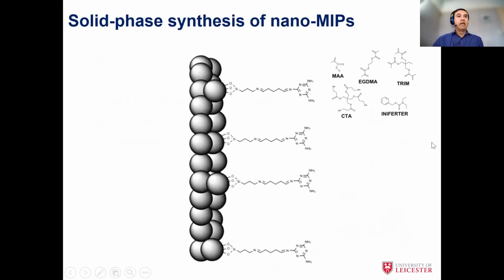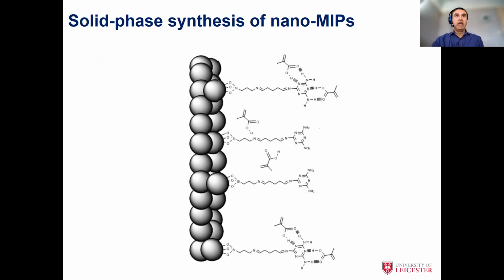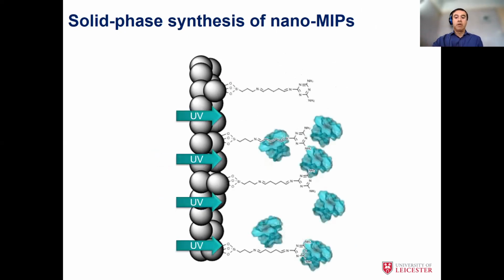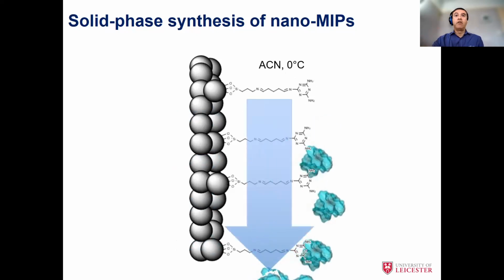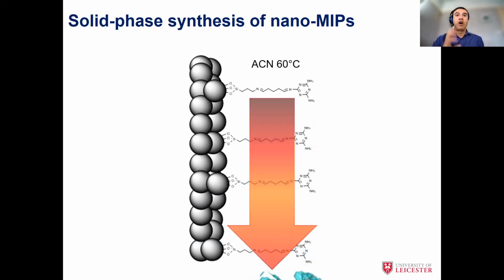Well, a very simple way is we use something called solid phase synthesis. So those of you that know a little bit about protein chemistry or about making peptides, we use solid phase synthesis in order to make our nanoMIPs. So these are just glass beads, which are very cheap and quite cost effective. And you covalently attach the target of your interest, which is your template. You add a variety of reagents, and then you shine UV light, so it passes through the glass, which induces polymerization. And then you have low affinity nanoparticles that are not really very useful, and you wash them away in acetonitrile here at quite a low temperature. And as you raise the temperature of the column and the solvent, you could then wash out and collect the high affinity nanoparticles. It's a very simple way of doing it.